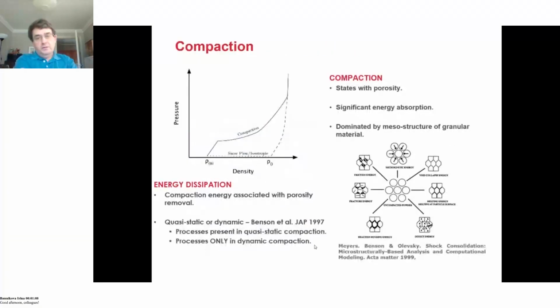So one of the key things about a powder is there's significant energy dissipation. You get quite hot material being produced because you've got localized friction between the particles. You have jetting of material within the voids. You've got this energy absorption due to that.